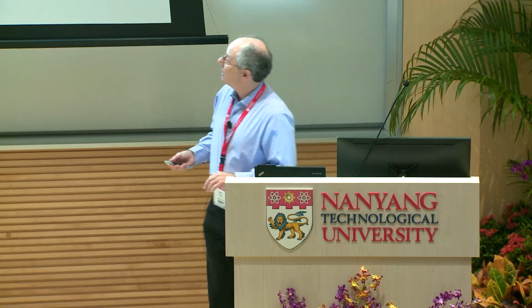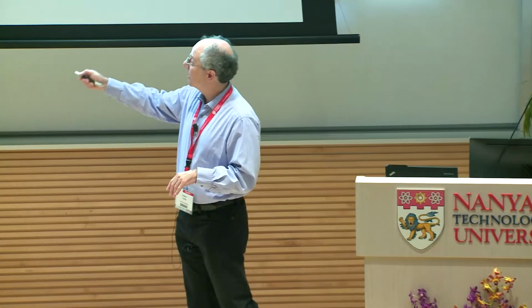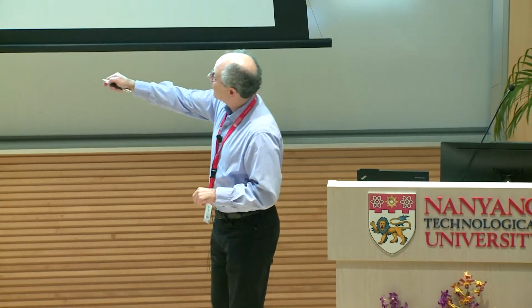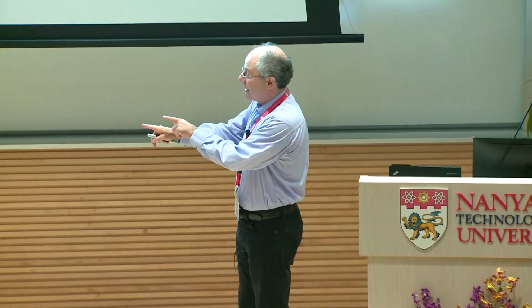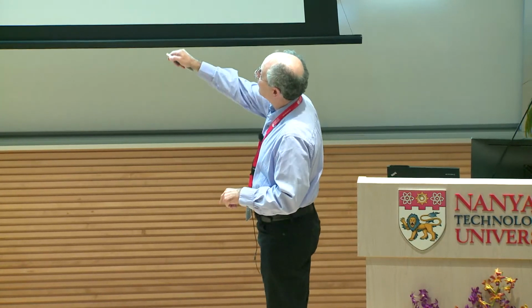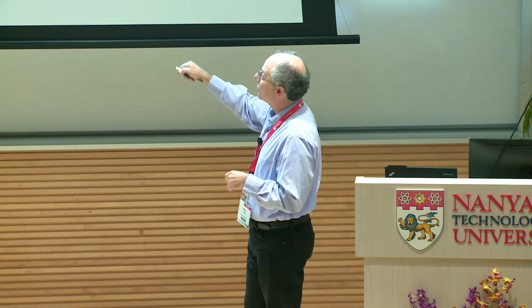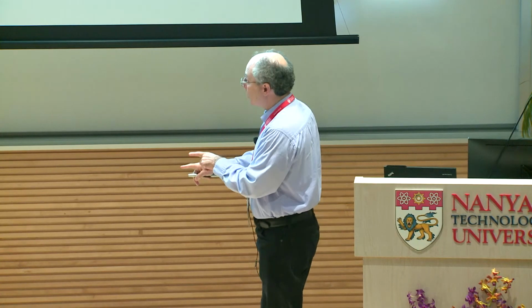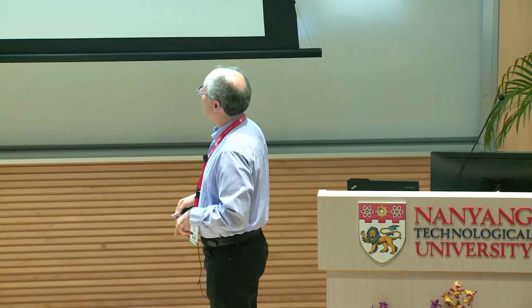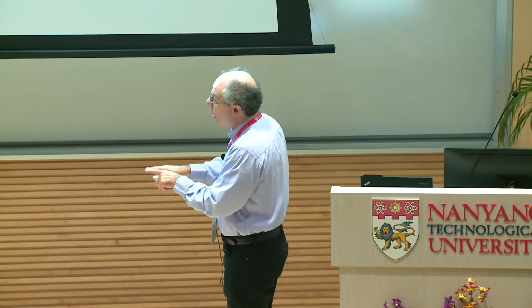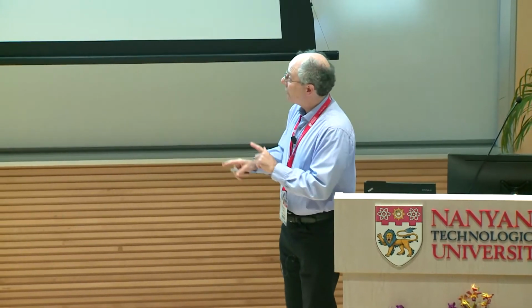Right, so one thing we did, a numerical thing, which lets us check the ferromagnetism at short distances, is to take this geometry, this model where we have 2/9 of the sites occupied, and basically turn the spins in different directions. And then we found a difference of energies that lets us look at whether the energy is raised by twisting these in opposite directions. And indeed, we find the energy always goes up as you twist these away from one another. So that tells us when impurities are close together, they'd prefer to be aligned.